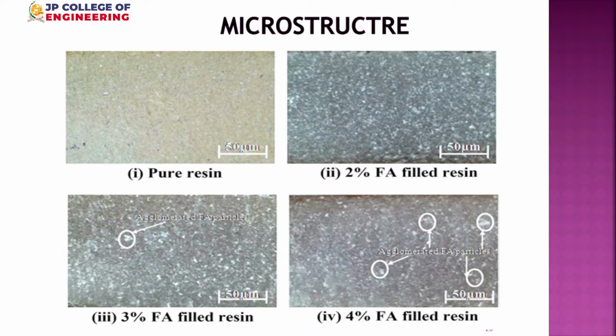Next slide, please. So this is our microstructural study. If you see the pure resin, we could not see any kind of features. But the moment you go to the 2% FA filled resin, you can see white dots. These are our fine fly ash particles. Those white dots indicate some amount of agglomeration will be there. Our objectives are coming down; the meaning is they agglomerate and the property will come down.